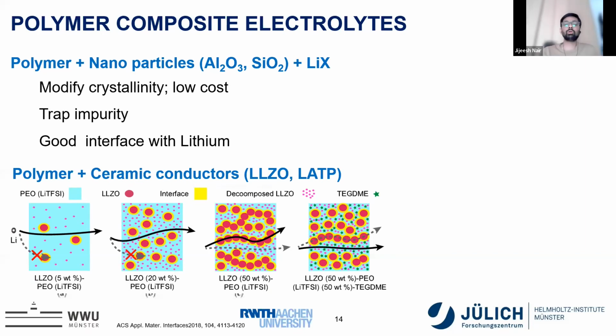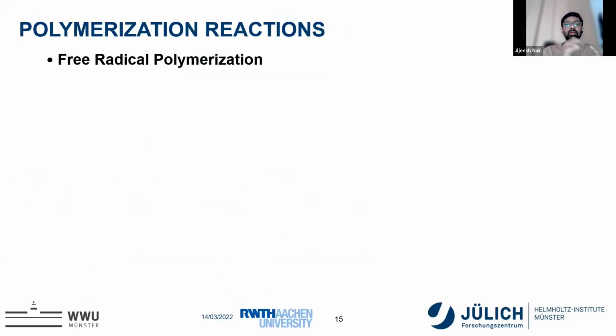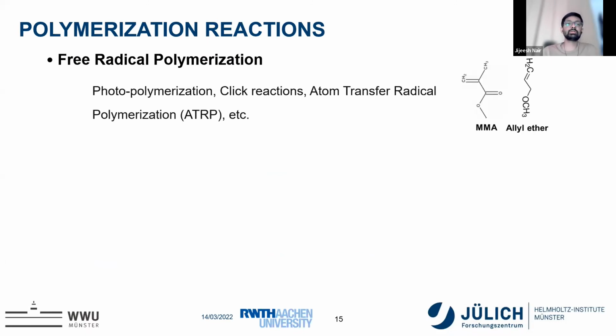So from polymer matrix, salt, polymer architecture, etc., you can develop polymer electrolytes. And from the polymer reaction point of view, if you look, mostly used is free radical polymerization. Especially in my case, I have been focused much on photopolymerization. However, there are other polymerizations like click reactions, atom transfer radical polymerization, or RAFT techniques, which you can use and you can engineer a polymer chain, whether it is a block copolymer or homopolymer, or different morphologies. And mostly unsaturated monomers are used.